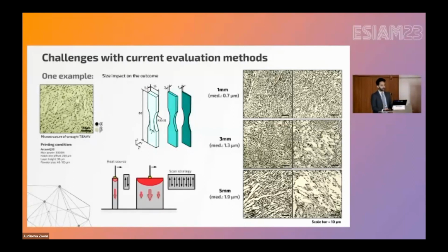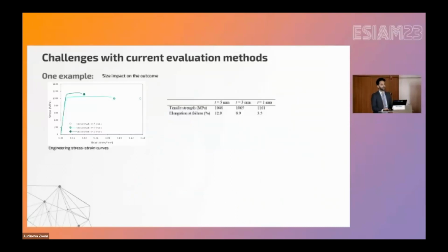Why is that? If we look at this schematic picture, we can see the larger the part is, on average, during fabrication, the temperature will be higher, and it will remain higher for a longer time, even though the energy density is the same, meaning that the grains have a longer time and a higher temperature to grow larger. What can it do to mechanical properties?